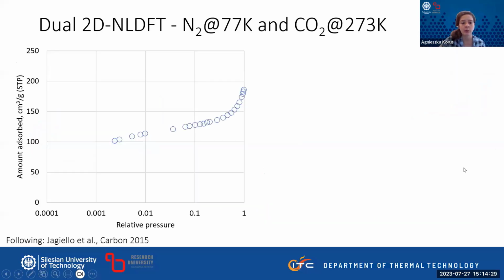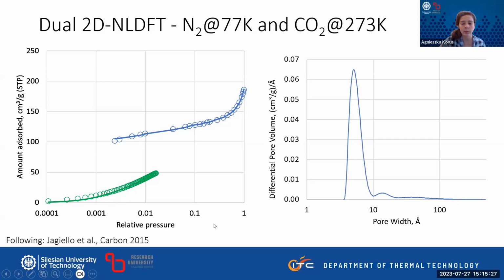So we've been doing this with the dual NLDFT model aimed at heterogeneous carbons that was developed by Jagiello et al. In this one, we use the nitrogen isotherm and couple it with the CO2 adsorption isotherm because this way you can skip the low-pressure part of the nitrogen isotherm, which is usually not very accurate and also really hard to measure. So you can use just the high-pressure part of the nitrogen isotherm, couple it with the CO2 adsorption isotherm, and then do the simultaneous fit to both kernels. You can get your calculated isotherms, based on which you can get the pore size distribution.